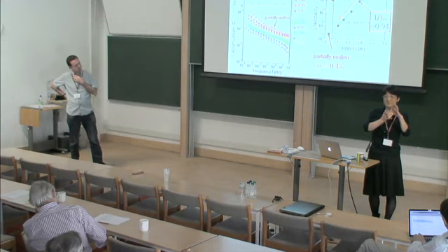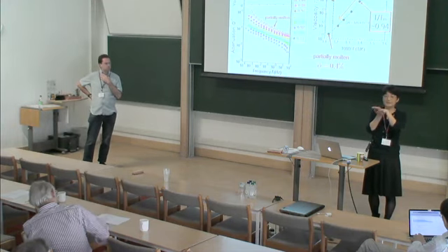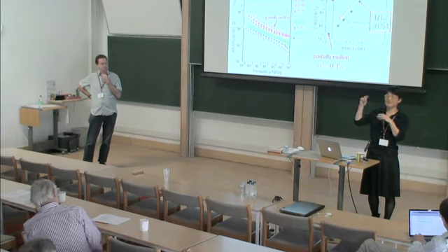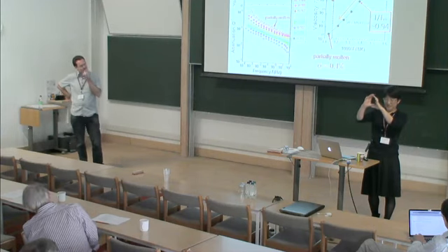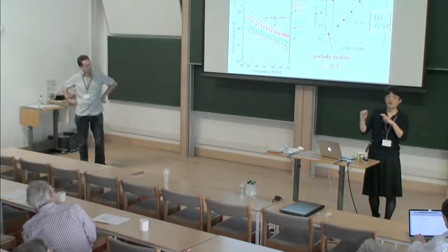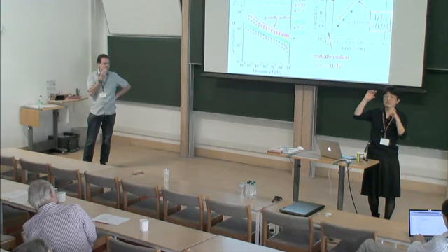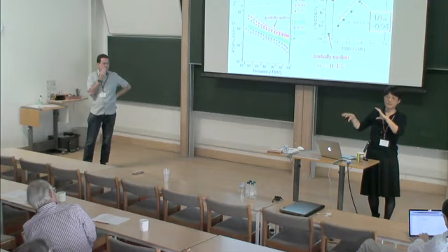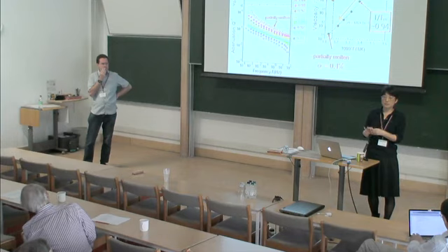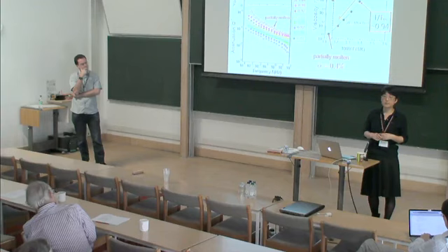The high VP/VS ratio is only for thin melt shape, and for equilibrium shape, VS perturbation over VP perturbation is about 1.5 or something. But in this grain boundary sliding, VS perturbation over VP perturbation will be more than 2, I guess, because the grain boundary phenomena cannot affect bulk attenuation. So maybe even higher VP/VS is expected for this mechanism.